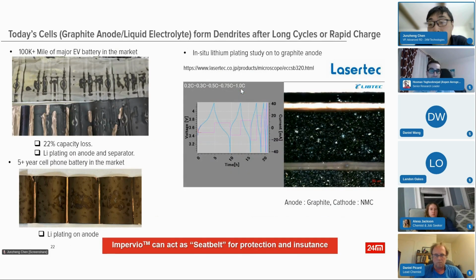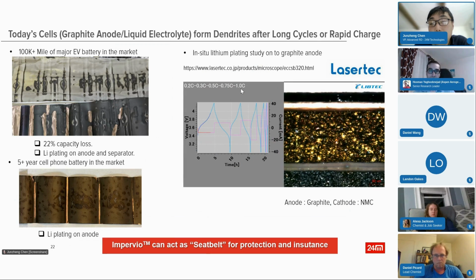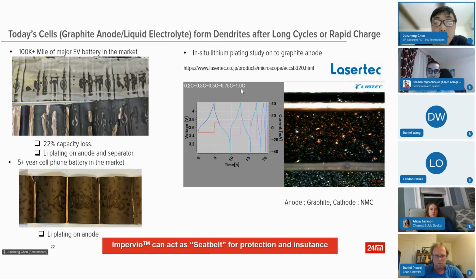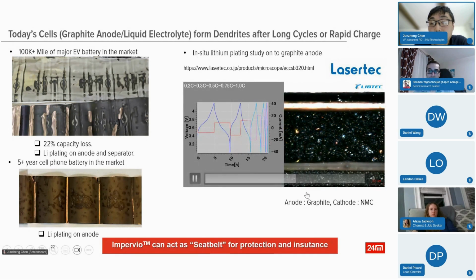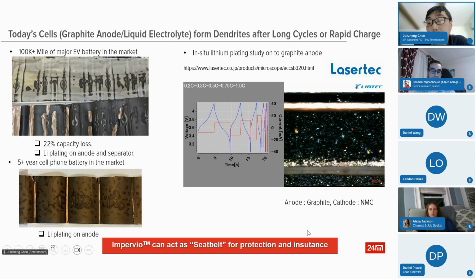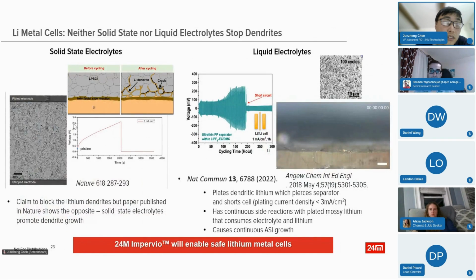Dendrite is the main issue we saw that causes these fires. For the fast charge cells, you can see the anode graphite at the beginning. If it's slow charge and discharge, there's no lithium plating, there's no dendrite growth. But when it goes to charge and discharge at a very aggressive stage, you see continuous lithium growth, and then it becomes irreversible in the end. So this is lithium growth at an initial stage, and in long-time use when the anode has failed, you see lithium growth too. Lots of strategies are used to block the lithium dendrite growth.